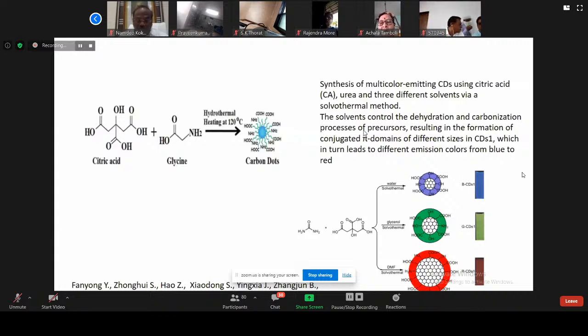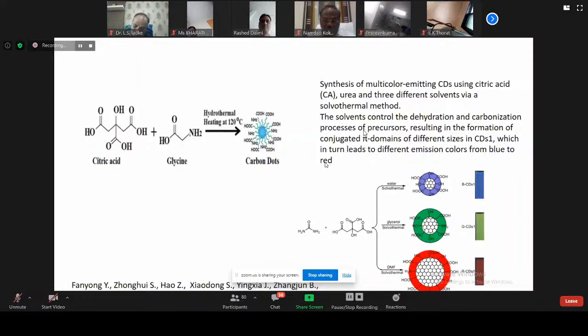Okay. Thank you. So this is another synthetic procedure from citric acid. When you look at the structure of the citric acid, it has carbon sources, citric acid and glycine, heated at a temperature of 120 degrees C. When we look at the old one, it was heated at a temperature of 180 degrees C. So the energy band gap is decreasing. So you see the link in this material. If I need a lower energy band gap, it simply means that I have to modify the surface of my carbon nanodots so that I will be able to get a lower energy band gap. But if I need a higher energy band gap, what does it mean? I need to reduce the functional groups on the surface. So all these things determine the kind of carbon nanodot that I'm going to have.